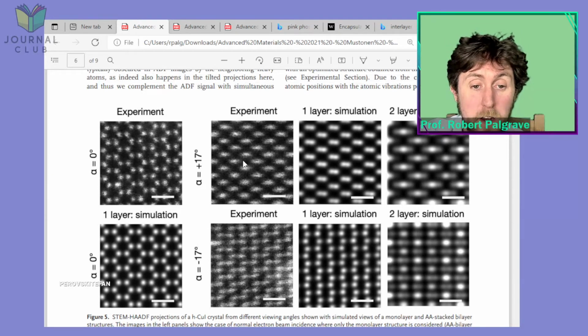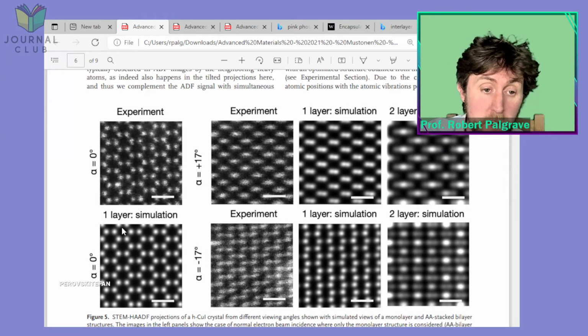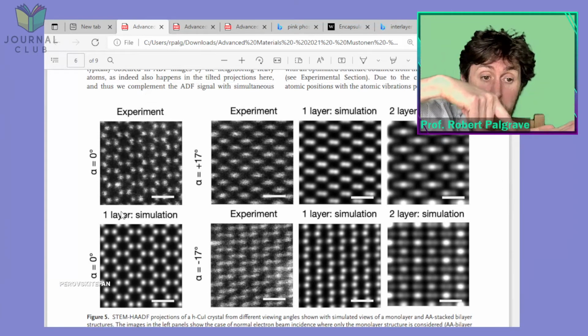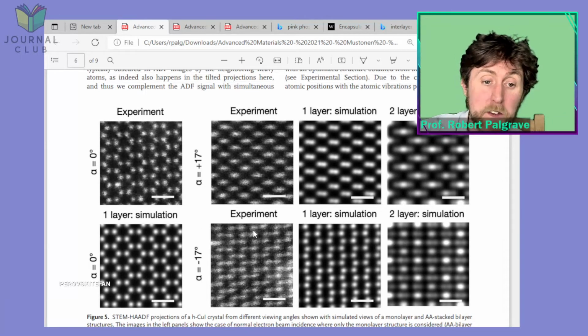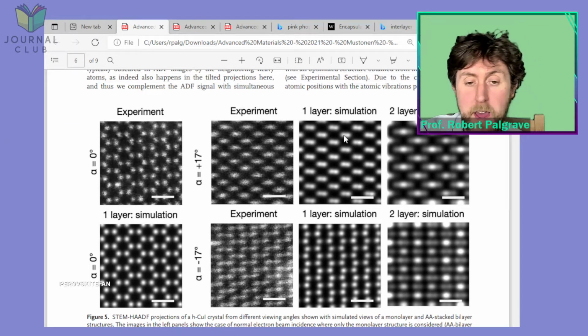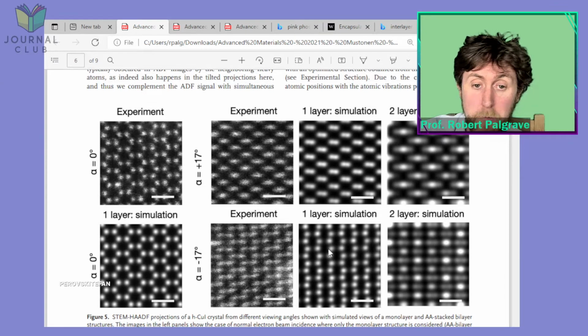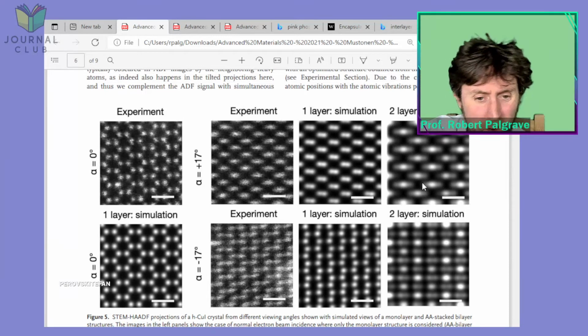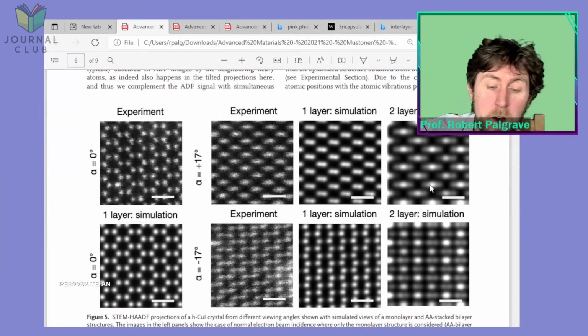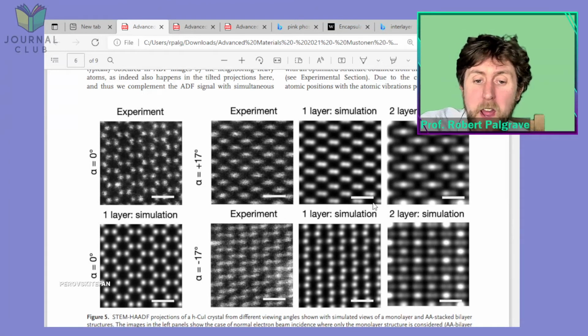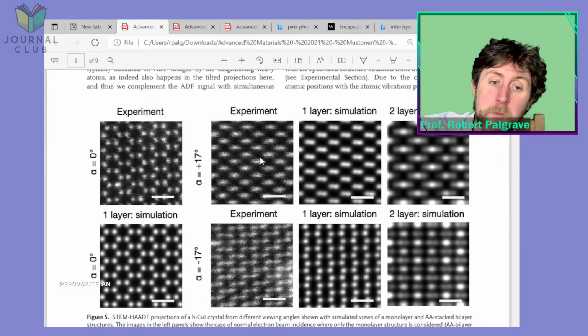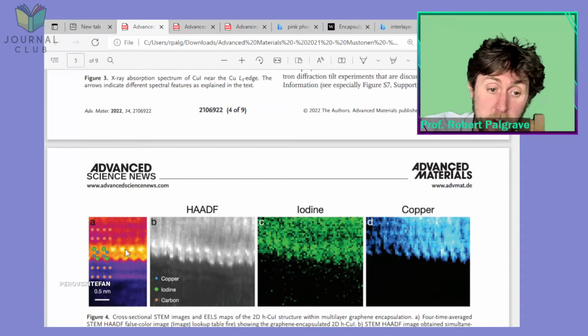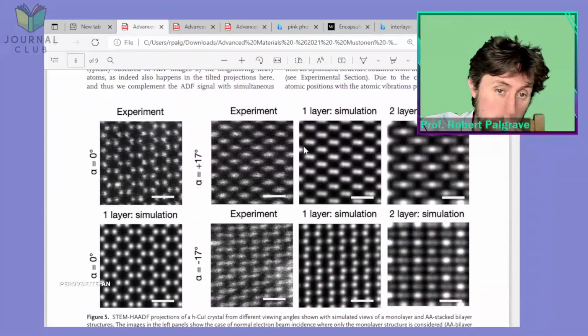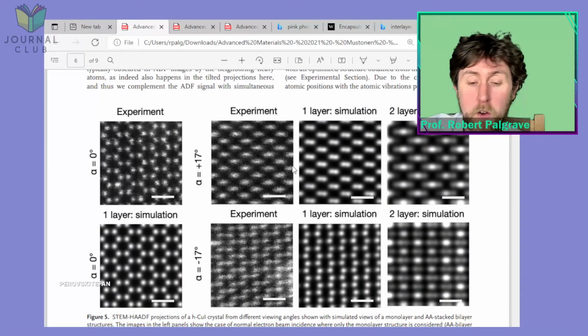I apologize, but it looks like, from both the perpendicular, the 0 degree experiment and simulation, and also both of the tilted experiments and simulations, the experiment matches up very well with the 1-layer simulation, and not that well. It's not a million miles away, but less well with the 2-layer simulation. So I think it's probably not nailed on just from this evidence, but combined with the evidence up here, which definitely looks like a single layer, this is giving a lot of weight to the idea that there's a single layer of this material here.